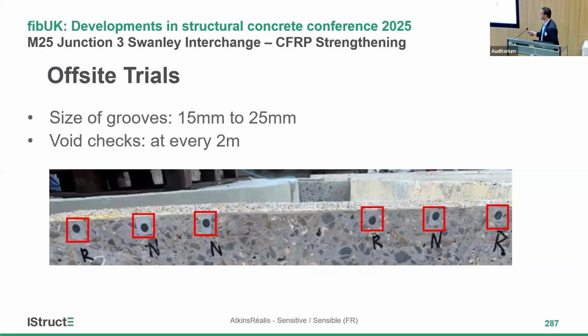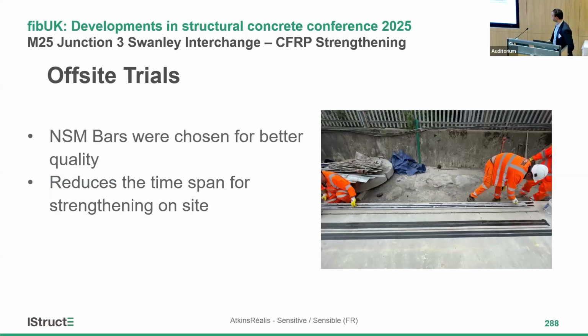We also explored the groove size varying between 15 mm to 25 mm, both in horizontal width and in vertical depth. Because we don't have any standard method to measure these voids, the next best option was to carry out destructive testing. So you cut the slab, which has been prepared off-site, at every 2 meters or 3 meters, and you check if you could find something. It was a positive result. There were no voids identified. So considering all this, NSM bars were chosen for better quality.